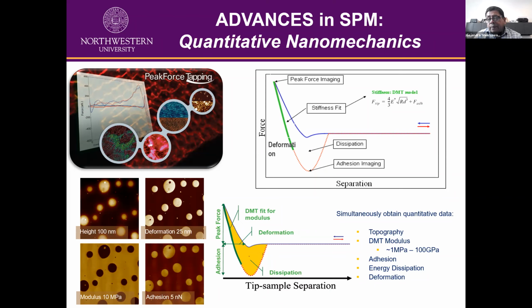intermittently brought together, similar to the tapping mode, to contact the surface, but for a short period, which eliminates the lateral forces, just like tapping. So unlike tapping mode, where the feedback loop keeps the cantilever vibration amplitude constant, in peak force tapping, it basically controls the maximum force. That's called the peak force on the probe. So this process prevents the tip from damaging the sample.